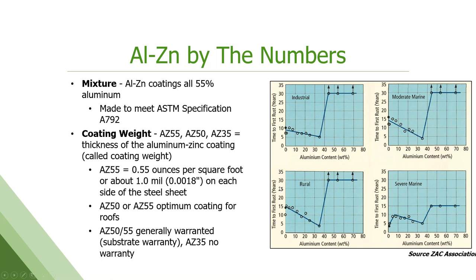The charts on the right here show the aluminum content by weight against the time to first rust. When they first developed this product, they were asking how much aluminum they needed. What they found is that the 55% that they ended up coming up with was really critical. You can see that at the lower weights, there's a big difference in performance as you jump that aluminum content up.